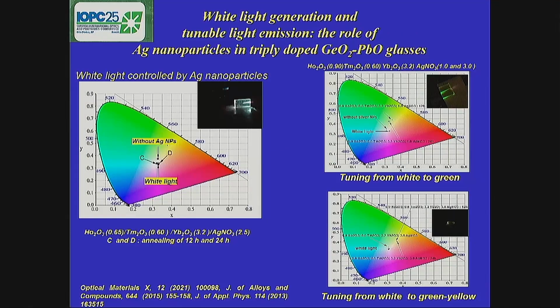Now I'll briefly show you some of the results that were reported recently. In this case, by adding silver nanoparticles to this germanate composition, doped with 3 different ions, thulium, holmium, and ytterbium, it was possible to generate white light. And by changing the concentration of these rare earth ions, we observed 2 different things: tuning of the light from white to the green region, and tuning of the light from white to the green-yellow region. And of course, these results are due to the adequate concentrations of the rare earth ions that emit in the blue, red, and green, the well-known RGB, plus the plasmonic effects of the silver nanoparticles that change the optical properties of the material.